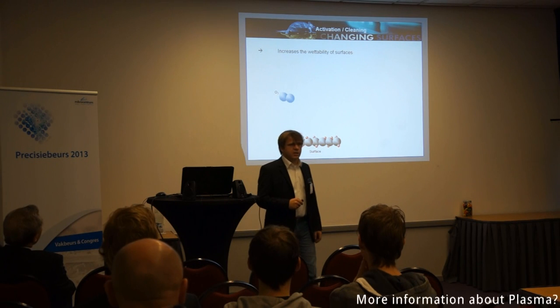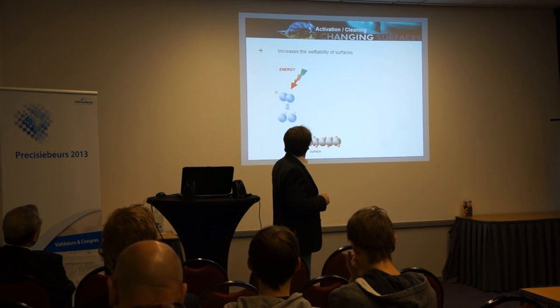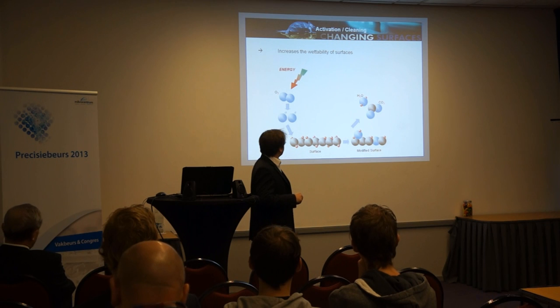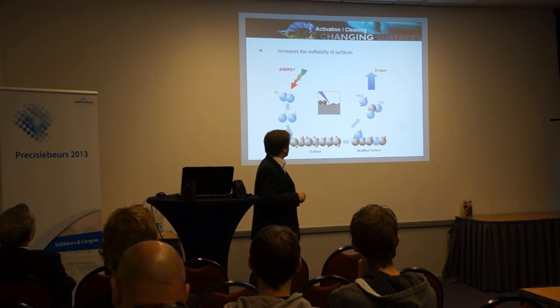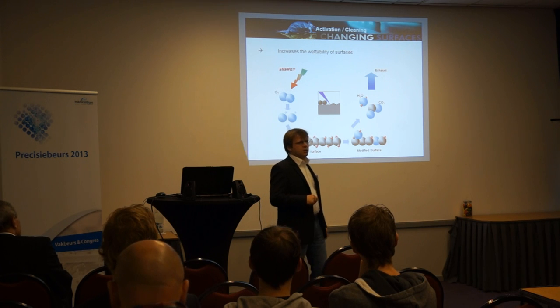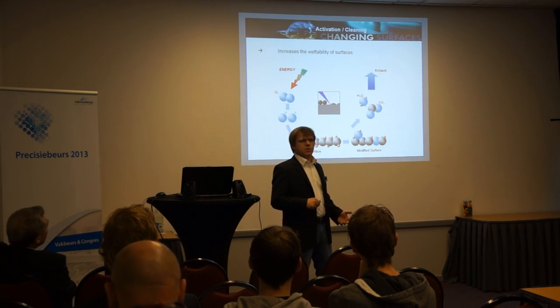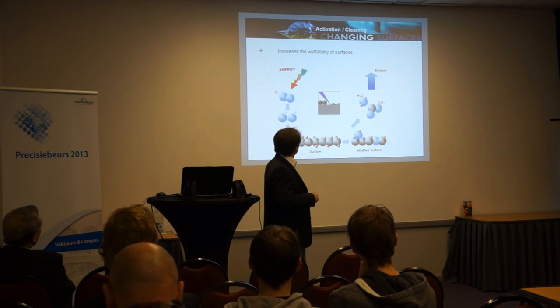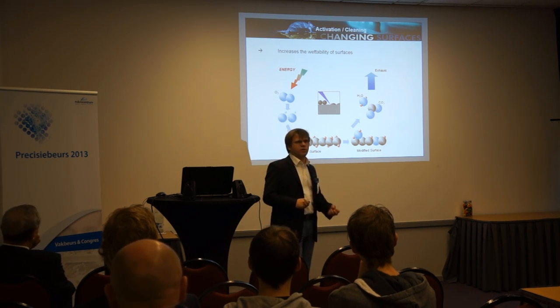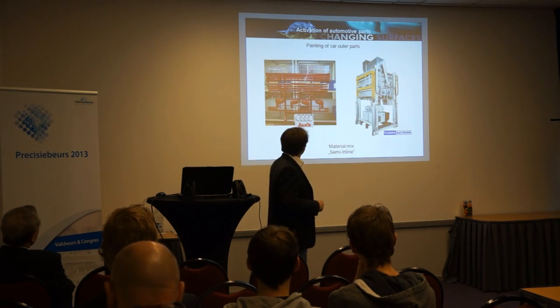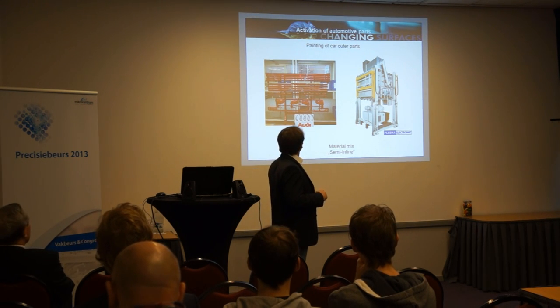When we want to do activation and cleaning, it's simply done by oxygen plasma. You have a surface, you make an oxygen plasma, you make radicals, and with these radicals you activate the surface. This means there will be OH groups, carboxyl groups, and other functional groups on the surface, making it polar — so it will be easier to paint, print, or whatever. This is the same principle as flaming of surfaces or atmospheric plasma. If there's hydrocarbon contamination on the surface, you can burn it off — it's a cold burning of contamination. You can even use it for plastics without any problem.